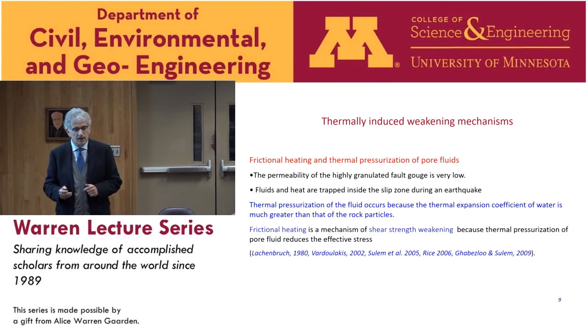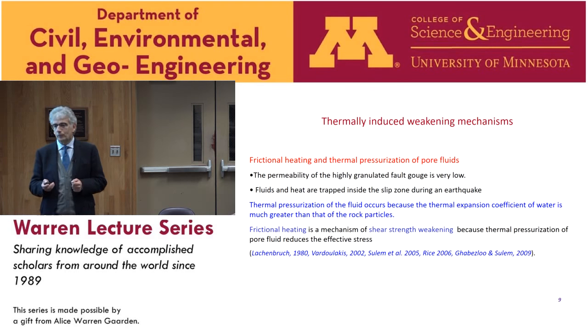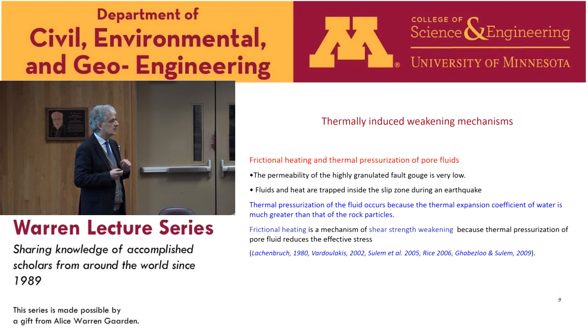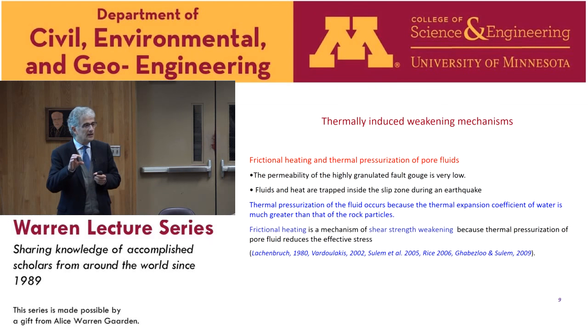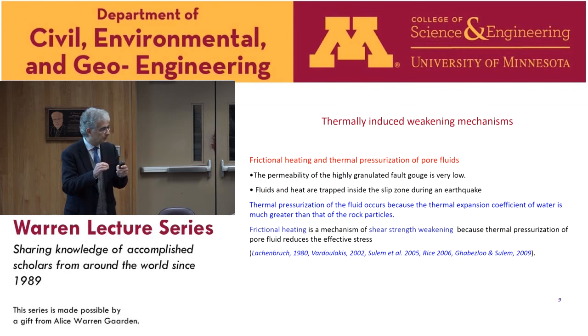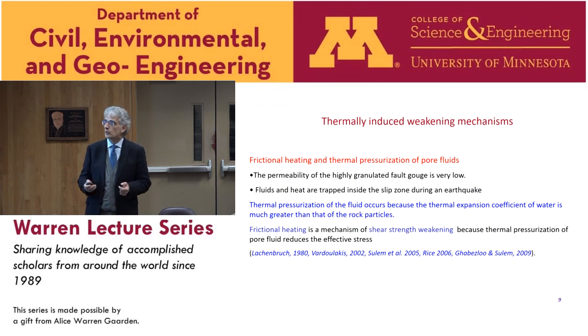First, the mechanisms related with the ubiquitous presence of fluids in fault zones. The core of the fault zone, which is made of this very granulated gouge, has a very low permeability, so that during a very rapid slip event, the fluid and the heat are trapped inside the slipping zone. And due to the fact that the thermal expansion of the water is much higher than the one of the grains, the water is actually caged into the solid skeleton, and this induces an increase of the pore pressure. So this is known as thermal pressurization of the pore fluid, which is due to frictional heating.